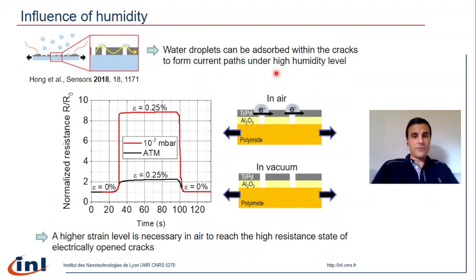Concerning the influence of humidity on the electromechanical response, Hong et al. have shown in 2018 that some water droplets can be adsorbed within the cracks to form current paths that decrease the resistance of the strain sensor under high humidity level. Here, we believe that a higher strain level is necessary to break this water droplet path in order to reach the high resistance state of open cracks.